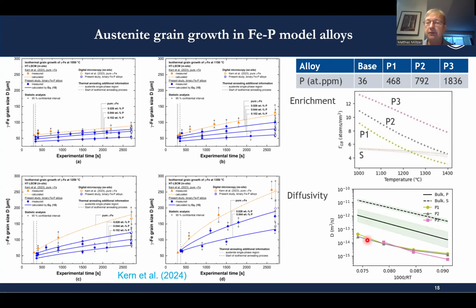And in our analysis, we found that for all phosphorus contents and temperatures, we get one diffusivity that again scales with the bulk diffusivity, maybe an order of magnitude smaller. So again, it's very similar to what I had just discussed for sulfur, that maybe this diffusion involving interstitial sites plays a role in having a lower diffusivity across the grain boundary as compared to bulk diffusivity. And we also have to keep in mind that obviously a lot of assumptions are made in all of this modeling, and there are also experimental errors involved in the grain size measurements, etc. So getting some sort of a consistent diffusivity is actually quite